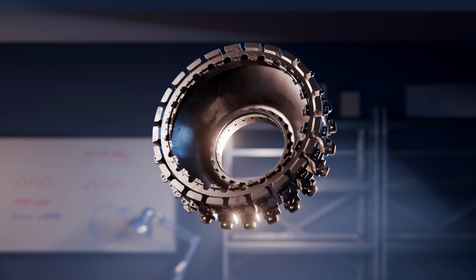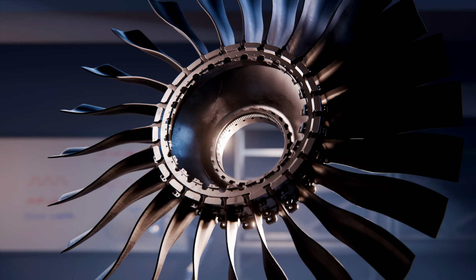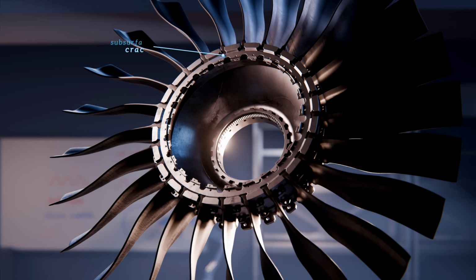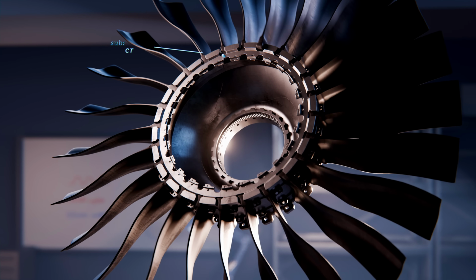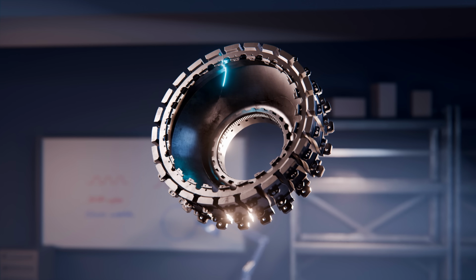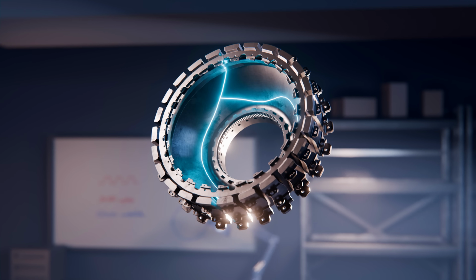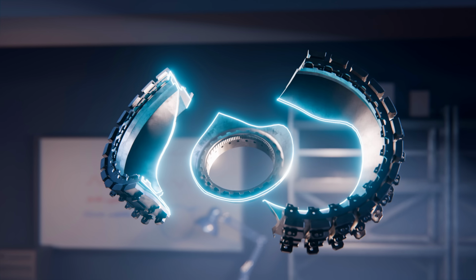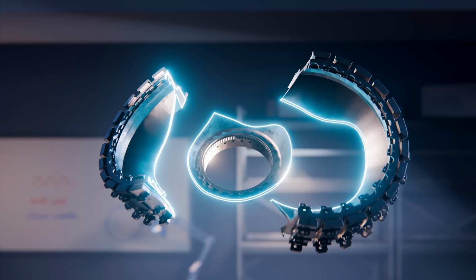They attributed the failure to a crack that initiated early in the life of the titanium fan hub and grew progressively until catastrophic failure. But this wasn't a conventional fatigue crack. The fan hub had failed just a quarter of the way into its expected life, based on normal fatigue assumptions.